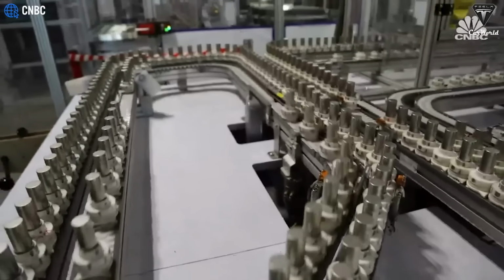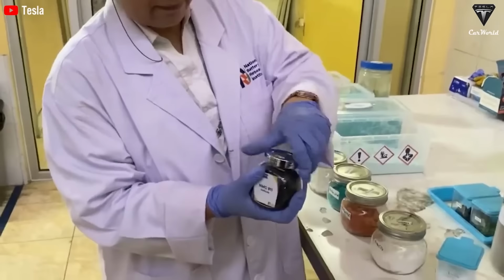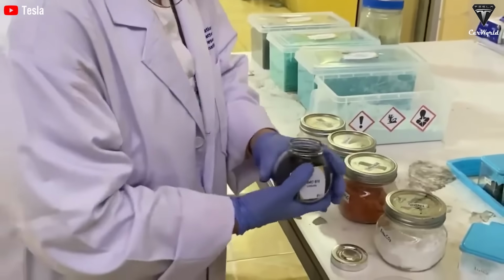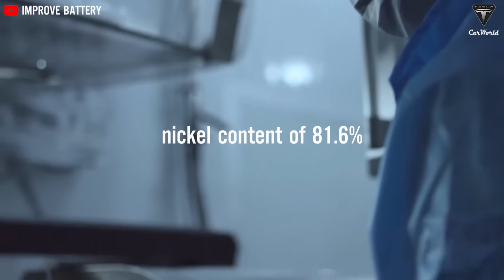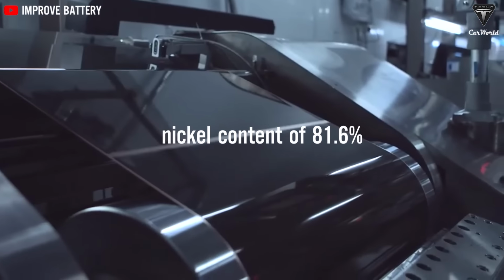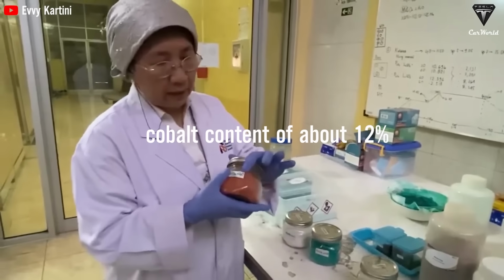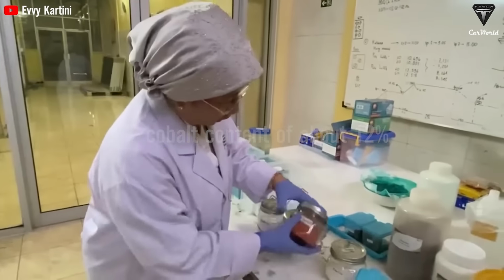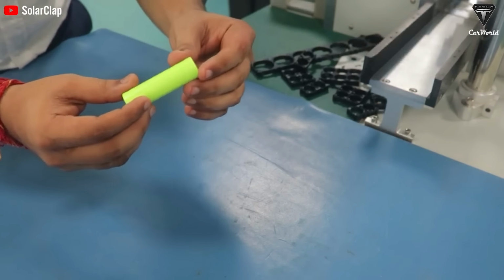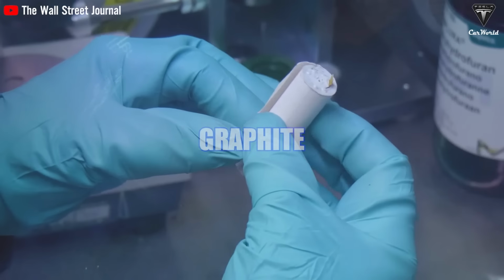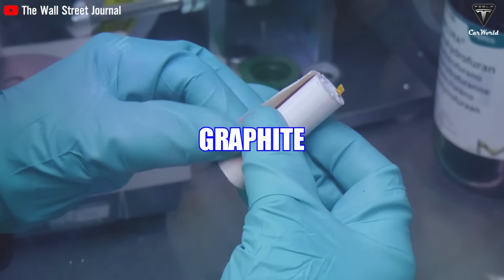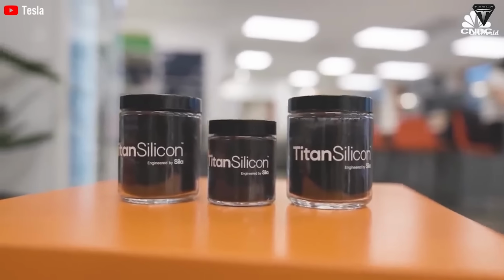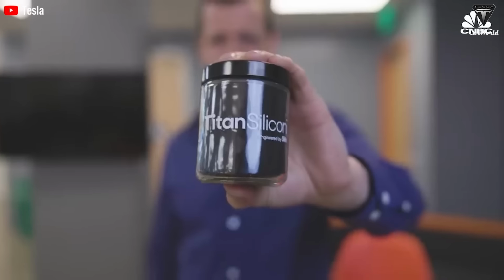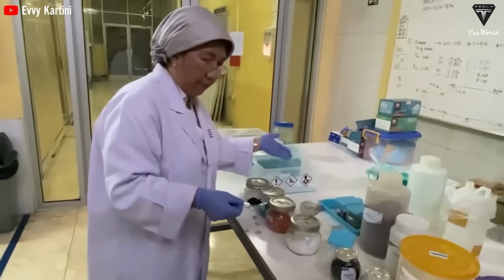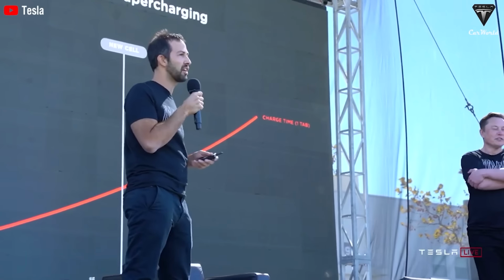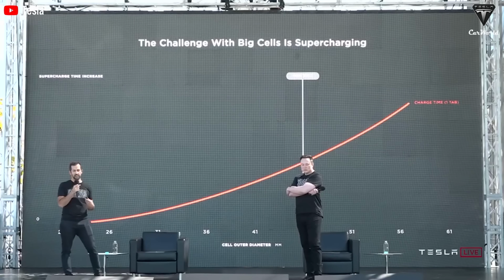The Type 4680 battery manufactured by Tesla is equipped with an NCM811 chemical cathode. Material characteristics show that the cathode has a nickel content of 81.6% and a cobalt content of about 12%. However, analysis of the anode showed that it contained no silicon. The active material at the anode is graphite. That was another surprise, as typically 10 to 15% silicon is added to the anodes of modern lithium-ion batteries to increase capacity energy density. This is considered Tesla's intention to become a pioneer in dry electrode technology.